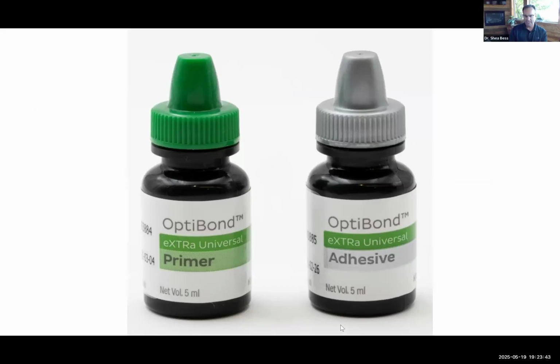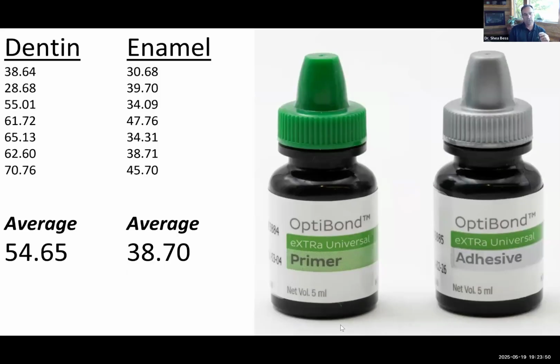Here's another product made by Kerr. This is OptiBond XTR, and this product has the second highest bond strengths to dentin that I found. So here's 7 specimens to dentin and 7 specimens to enamel. And if you look at this bond strength to dentin, 54, we're closing in on 3 times the bond strength of G-Bond to dentin if you simply use OptiBond XTR. I think that this is a fantastic product. And like I said, second highest bond strengths to dentin that I found on any of the 20 adhesives that